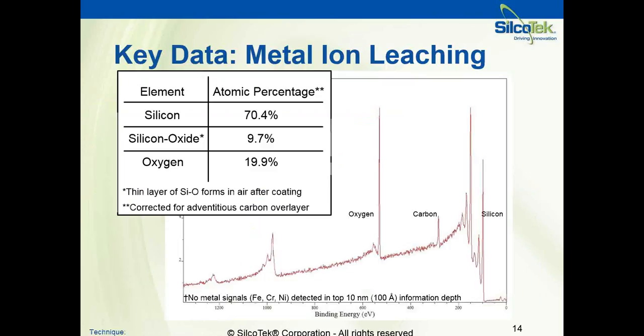And then just to show, again, the fact that metals and ions from the metals are not leaching out of the bare substrate into the process stream, you can see this XPS data from the cutaway that we showed before. So what you're seeing is only the elements of the coating. There are no iron, chrome, or nickel detected whatsoever in the top 10 nanometers of the surface.